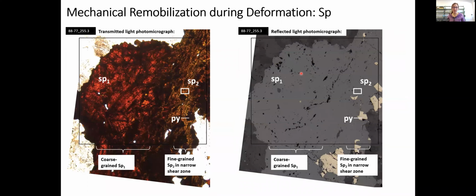Now, as another example, here we have some coarse-grained hydrothermal sphalerite. We've got a transmitted light photomicrograph on the left and reflected light on the right, same picture. And you can see this really coarse-grained sphalerite, which is quite dark red, and it's cut by a zone of paler orange sphalerite. That doesn't show up very well in the reflected light photomicrograph, but you can see chunks of pyrite sitting there.